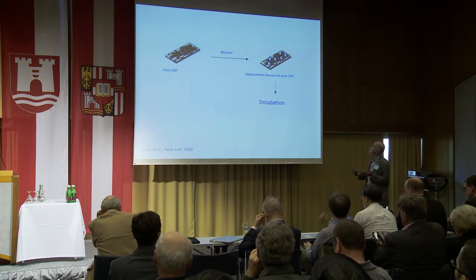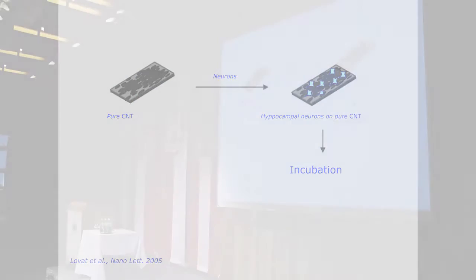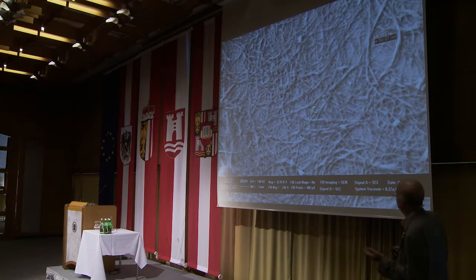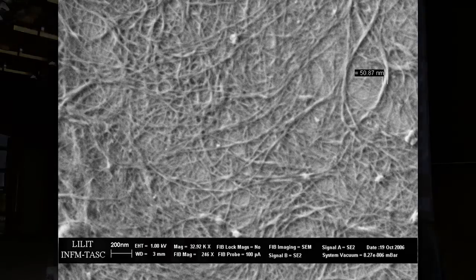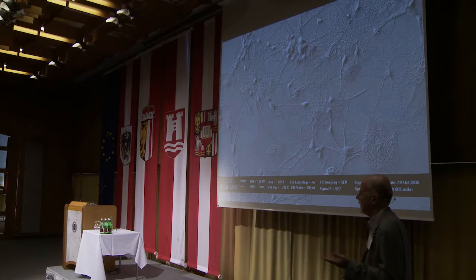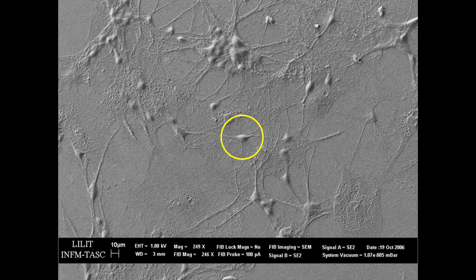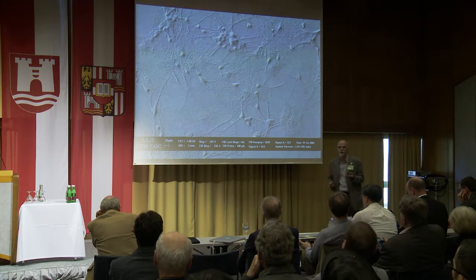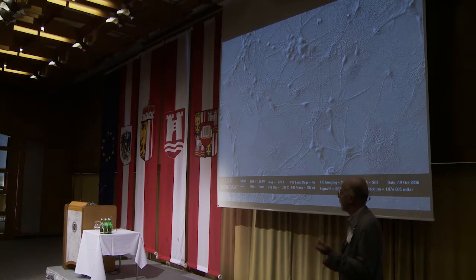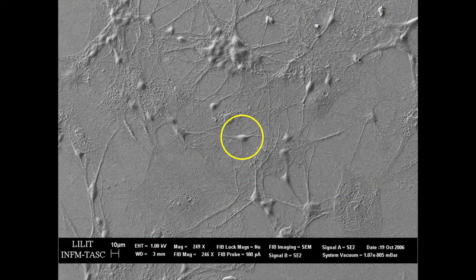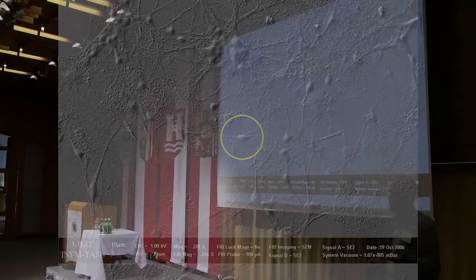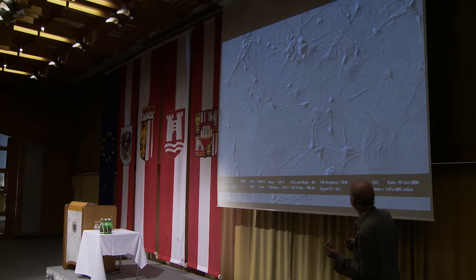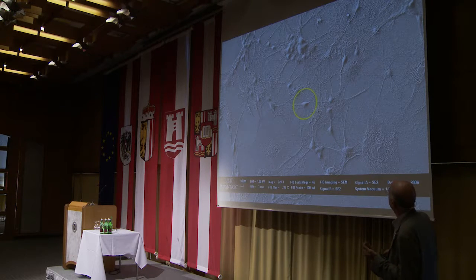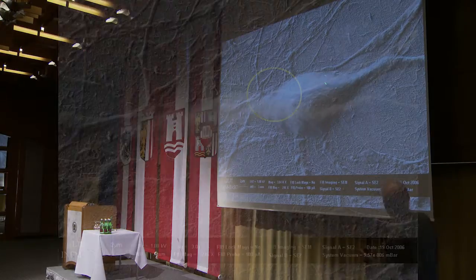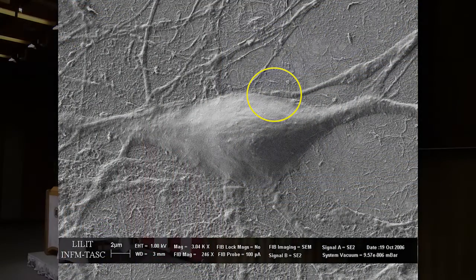And then we grew hippocampal neurons on pure carbon nanotubes, and let them incubate. What we can see is that the layer of carbon nanotubes is very homogeneous, and neurons grow very normally and very efficiently on carbon nanotubes. The shape of the neurons, the elongations, are natural. So the substrate of carbon nanotubes is a perfect substrate for the growth of neurons. In general, neurons try to communicate electrically with other neurons, so they elongate their dendrites in order to reach other neurons and start communicating with them. If we enlarge this image, we can see that this neuron is probably having a synapse here with this elongation of the other neuron.